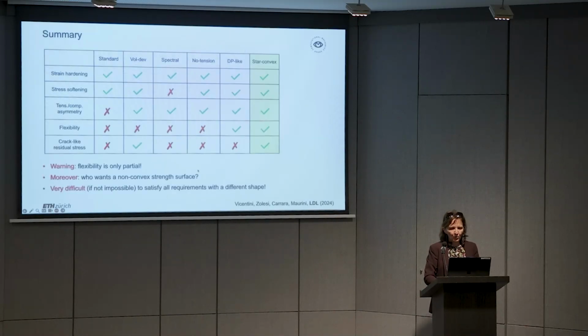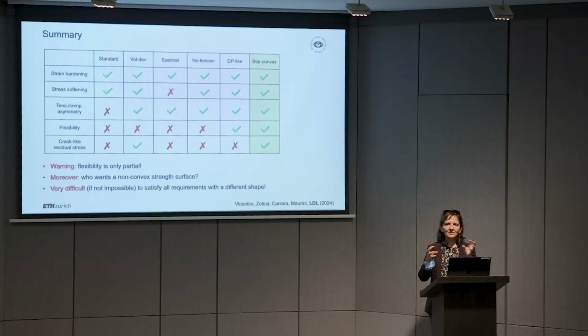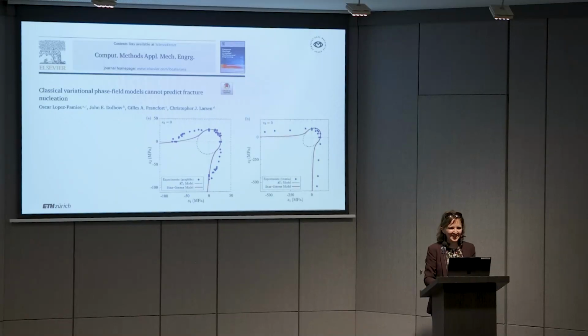Okay, one could think, why don't you look for another energy decomposition to do something better? The point is that the star-convex was found after a very long study where my student was actually frustrated for a while. It was essentially impossible, at least we couldn't do it, to satisfy all the requirements. So as soon as you adjusted some requirement, you had issues with another one. So to the best of my knowledge, the star-convex shape is the best you can do. It's the only way to accommodate all requirements. As soon as you get out of that, you're killed by something else. So we were aware that with the energy split approach we had come to the end of the story there. So we had to do something very different to make really one step forward. And this is what I want to talk about in the remaining 6 minutes I have.